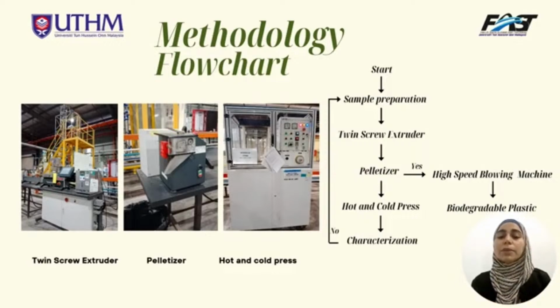LDPE. After preparing the sample, we need to pass that sample to a twin screw extruder to get homogeneous extrudates. After getting the homogeneous extrudates, we need to pass them to a pelletizer to get pellets of equal size. Then those pellets were put into the mold and placed in the hot and cold press machine to get the thin film for characterization.